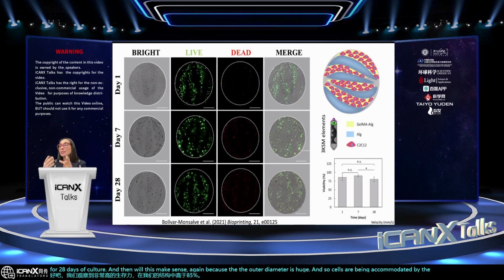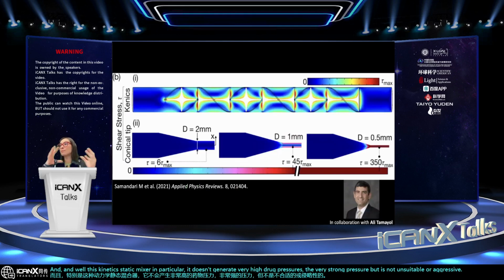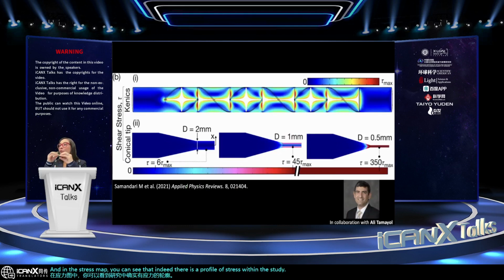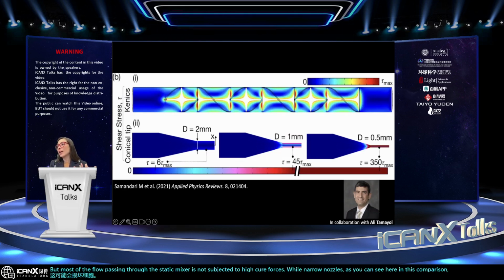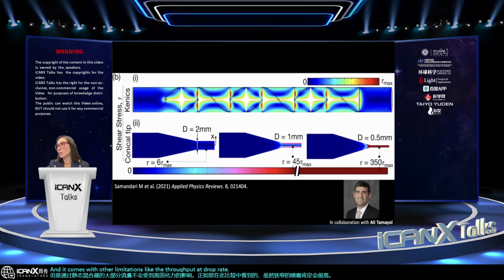And well, this Kenics static mixer in particular doesn't generate very high pressure drops. There is a pressure drop, but it's not unsuitable or aggressive for the cells. In the shear stress map, you can see that indeed there is a profile of shear stress within the static mixer. You can notice that there are a few red spots that could damage the cells, but most of the flow passing through the static mixer is not subjected to high shear forces. While narrow nozzles, as you can see here in this comparison, definitely are going to be very high, and that comes with other limitations like throughput, pressure drop, and limited resolution.